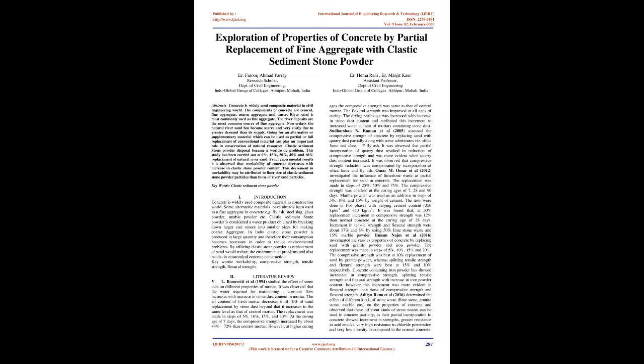Sudarshan and Raman et al., 2005, assessed the compressive strength of concrete by replacing sand with quarry dust partially along with some admixtures viz. silica fume and Class F fly ash. It was observed that partial incorporation of quarry dust resulted in reduction of compressive strength, and this was more evident when quarry dust content increased. It was observed that compressive strength reduction was compensated by incorporation of silica fume and fly ash. Omar et al., 2012, investigated the influence of limestone waste as partial replacement for sand in concrete.